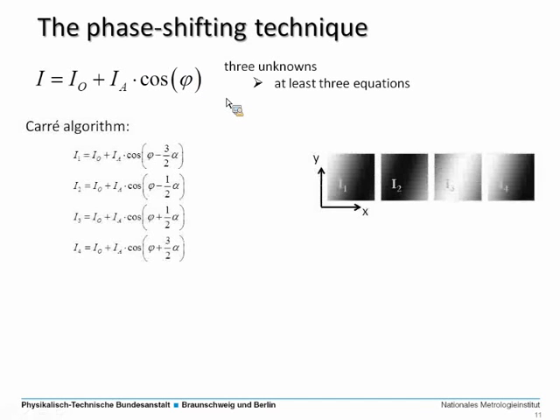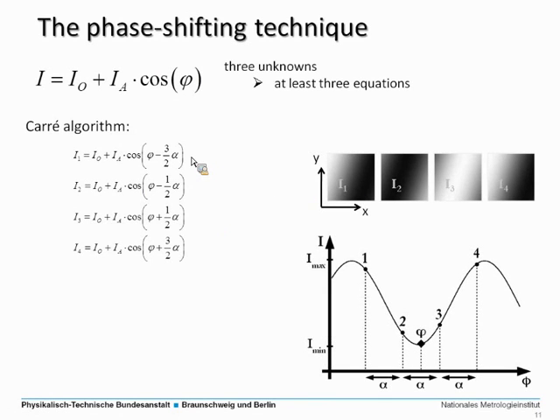So you have to use this so-called phase shifting technique in order to evaluate the phase. And for instance, you can use this Carré algorithm. There are a lot more algorithms, but I chose this as an example because it's one of the easiest ones. In this case, you use 4 equations because you have one quantity more, this alpha here, and this alpha is related to a phase step which is used during the measurement when you record a series of 4 interference patterns. You see here on the right hand side.